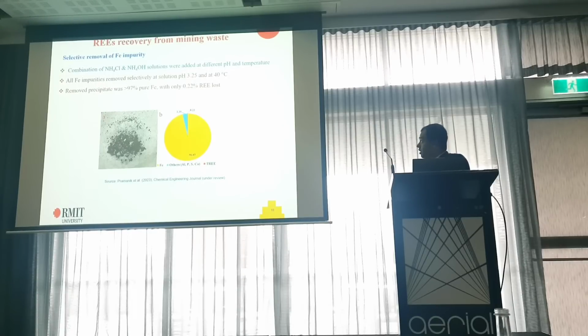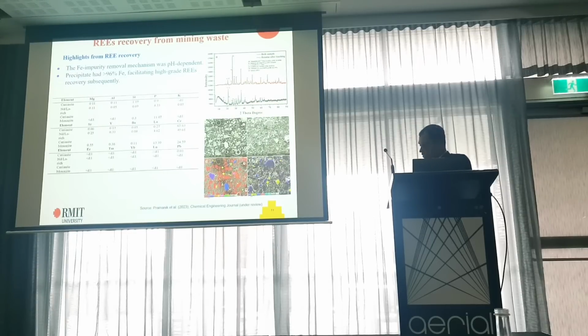After working at different pH and temperatures, we understood that more than 97% of the iron we are able to separate from the rare earth. If we talk about the mass loss, when separating iron from the sample, only 0.22% of rare earth was lost. In principle, we can say that the iron impurity removal mechanism was almost pH dependent, and